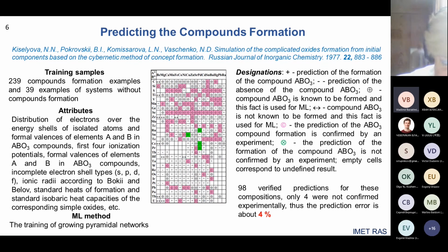Over the past years, many of these composition compounds have been obtained, and it became possible to compare our predictions with the new experimental data. From the 98 verified predictions for this composition, only 4 were not confirmed experimentally. Thus, the prediction error is about 4%.